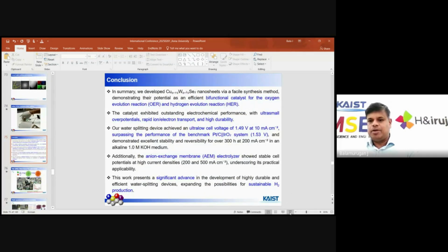From the studies, we can say the cell voltage is lower than the commercial catalyst's 1.53, with our catalyst at 1.49. We also made an anion exchange membrane device like a commercial one, and tested at different high current densities. From the studies, we can get high sustainable hydrogen production. So we think this catalyst may be commercialized easily because of the high current density, lower overpotential, and high durability.